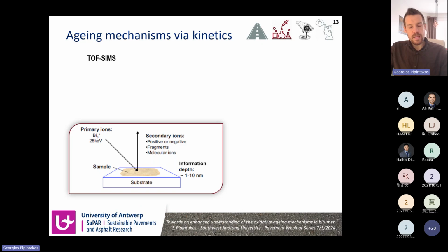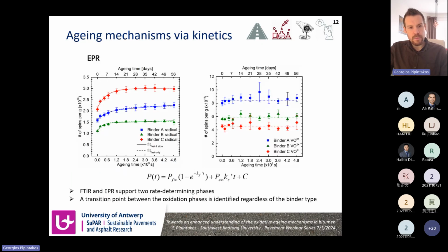So the transition point from the previous graph and from FTIR was found around 8 days. So 8 days, and the transition point is the completion of the fast rate phase, of the rapid phase, and the initiation of the slow rate phase. So 8 days is considered as the transition point for all the binders based on this study.